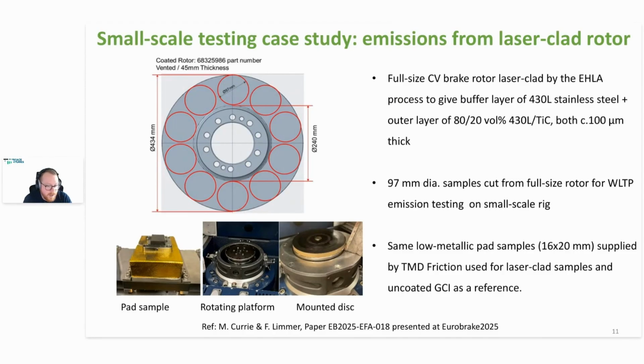The small 97 millimeter diameter samples were cut from the disc and were tested against a standard low-met friction material over 8 full WLTP cycles. Friction, wear, and emission results were compared with those for corresponding uncoated gray cast iron discs as a reference.